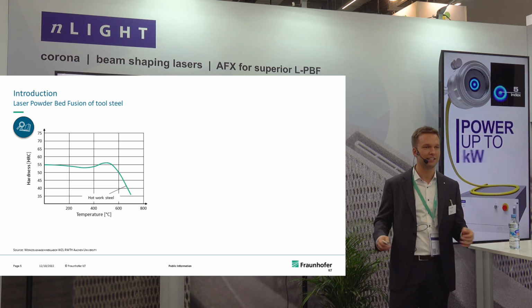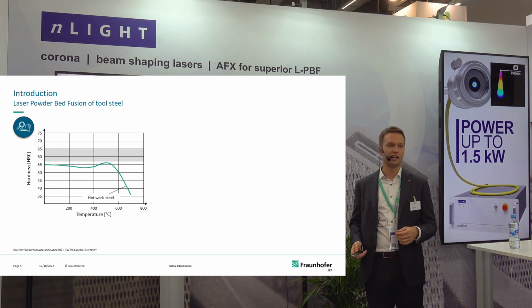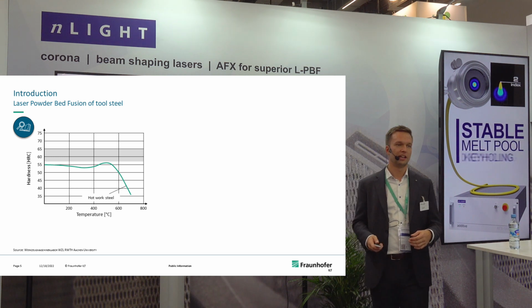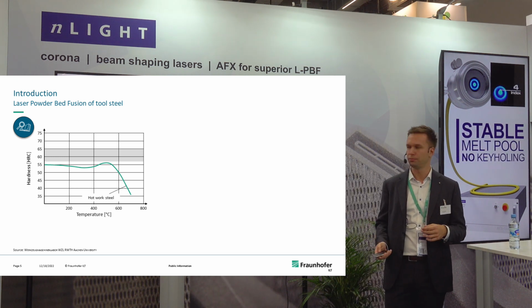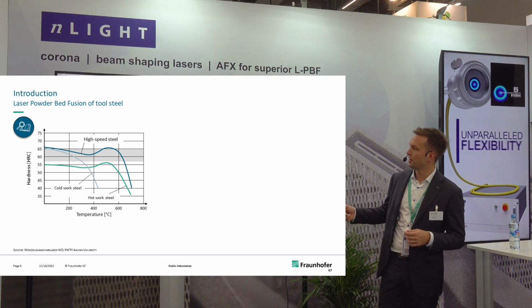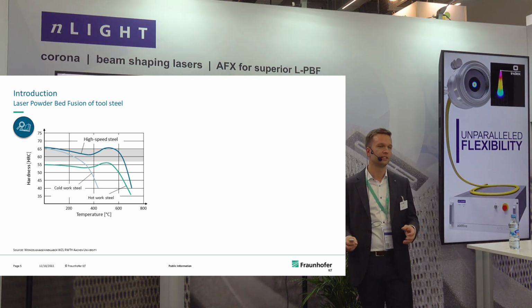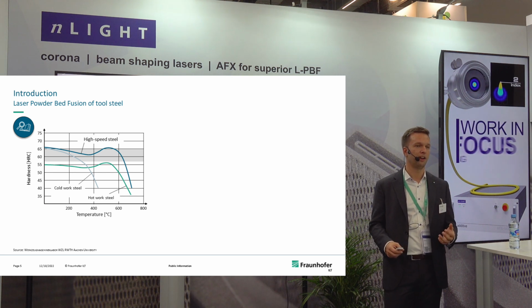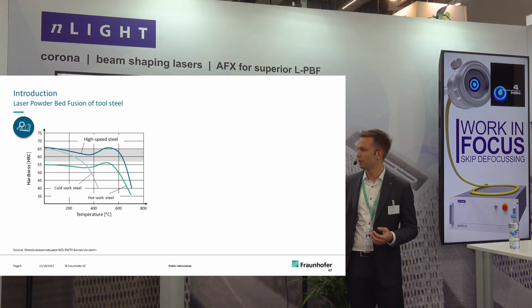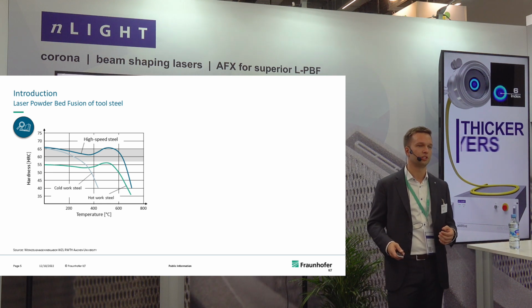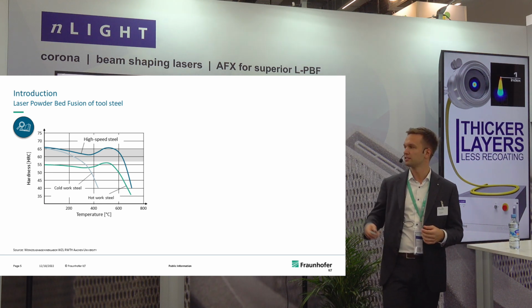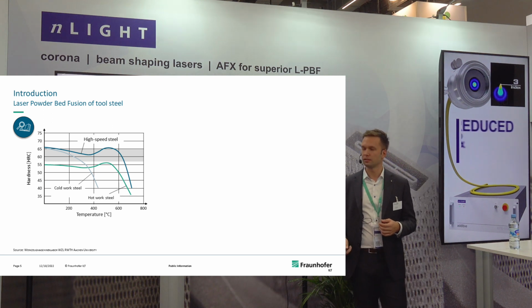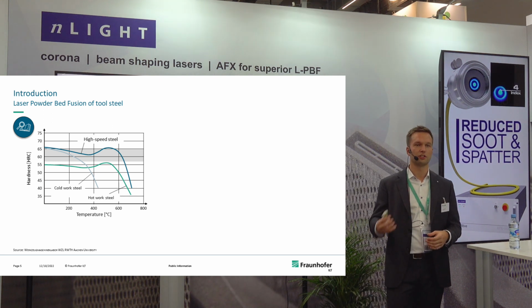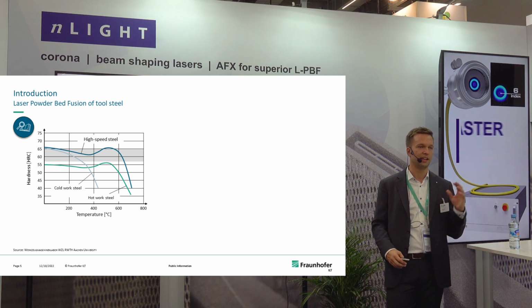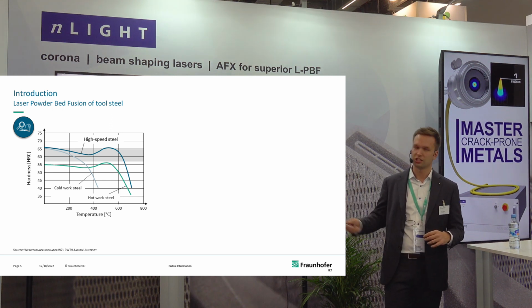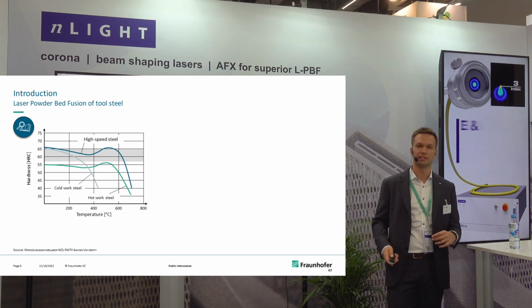So when you look at tool steel, very commonly used word, tool steel doesn't necessarily always mean tool steel. There is a variety of tool steels that can be categorized according to their hardness, of course, and also to their maximum operating temperature. So when you look at this graph, you see there is cold work tool steel, which is fairly good in terms of L-PBF processing, but lacks the properties, especially at elevated temperatures, and loses its hardness over the temperature. For hot work tool steels, there are also some examples that can already be processed at elevated preheating temperatures, such as H11 or H13 tool steel.